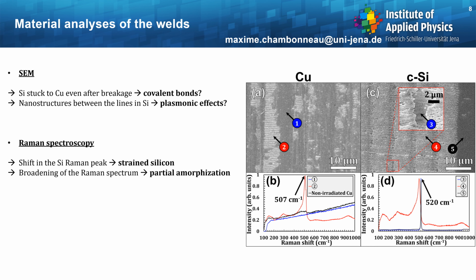Ultimately, we have carried out material analyses of the welds. So first, concerning the copper sample, we have noticed the presence of silicon stuck to the copper sample even after breakage, here in white, which may indicate the presence of covalent bonds. Concerning the silicon sample, we have noticed the presence of nanostructures between the lines corresponding to the scans, which may indicate the importance of plasmonic effects during the welding.